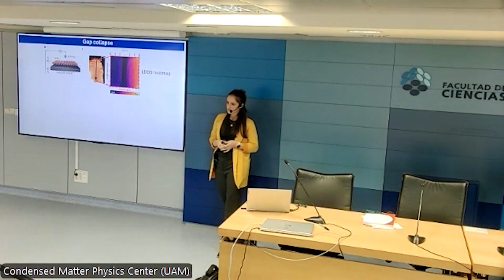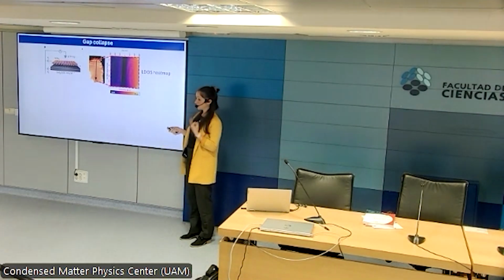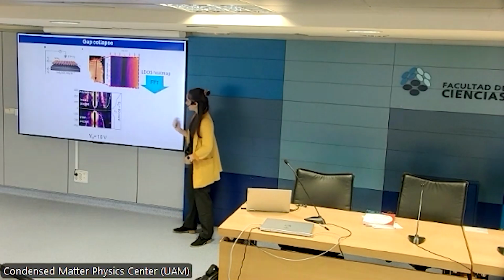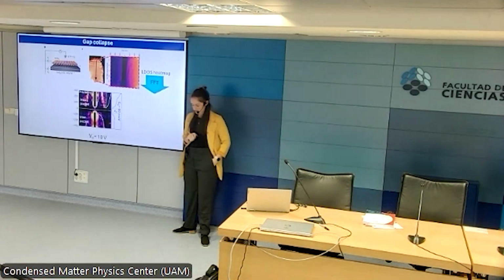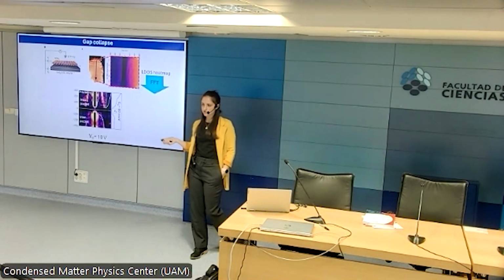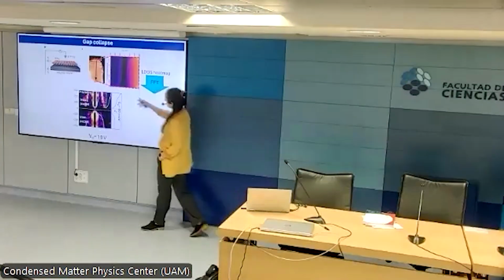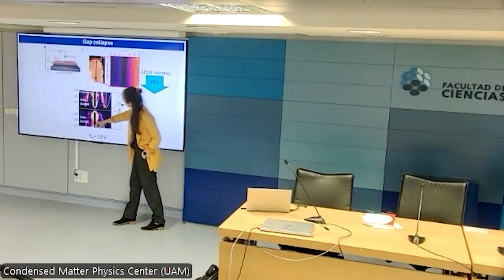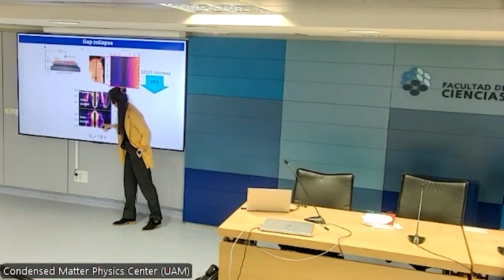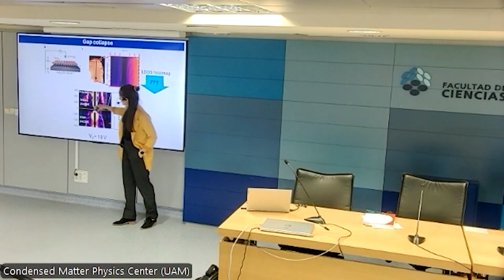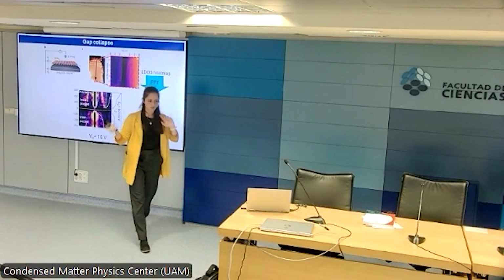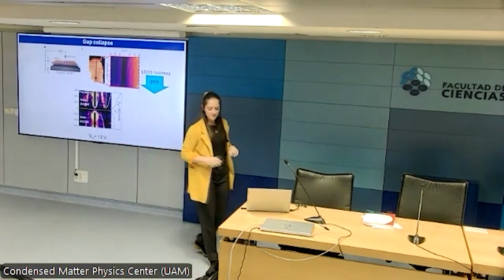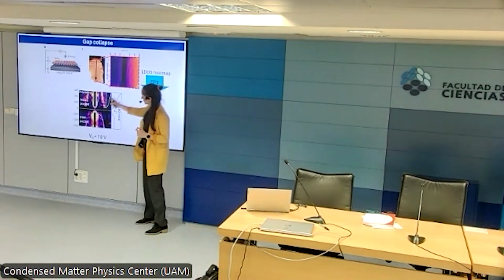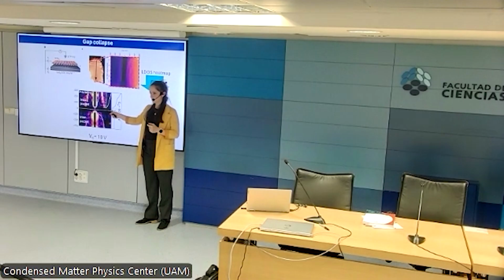Of this local density of states map, we take a one-dimensional Fourier transform, which tells us what are the scatterings that are allowed in our system, and sort of allows us to reconstruct the band structure. If you can see, by doing the FFT of this, we find one valence band here. This is the bottom of the conduction band. There's 3 pockets because there's intra-pocket and inter-pocket scattering. Let's not go into the details. But you can see that, if you integrate this, there's a hard band gap of 60 meV.